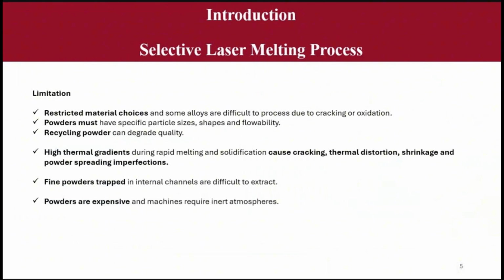So, the limitations. The limitation is restricted material choice, and some alloys are difficult to process due to cracking and oxidation. Powders must have a specific particle size, shape, and flowability. Recycled powders can degrade quality. Another kind of limitation is the high thermal gradients during the rapid melting and solidification, which cause cracking, thermal distortion, shrinkage, and powder spreading imperfections.